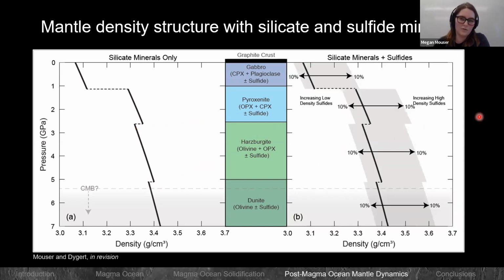If we add sulfides into the mix, this starts to change things quite a bit. Some studies suggest that maybe there was up to 10% weight of sulfides in the interior. What I'm showing here is not saying that there is 10% sulfides in every single layer. It's just showing what would happen to each layer if you added up to 10% of the high density sulfides or some of those low density sulfides.